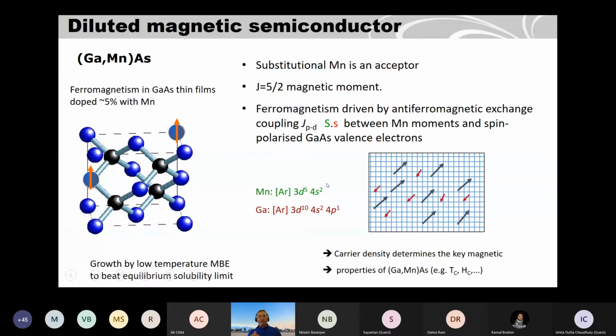So if we go back, let's say 20 years from now, we have seen that people have used magnetic impurities up to 5%, for example, manganese atoms in gallium arsenide. These are substitutional atoms, the manganese. Manganese have magnetic moments, and these magnetic moments are understood to be interacting by the carriers like electrons or holes in this gallium arsenide. So it's a carrier mediated magnetism in this gallium manganese arsenide, and the Curie temperature is around 150 or 200. So people are still sometimes working on this.